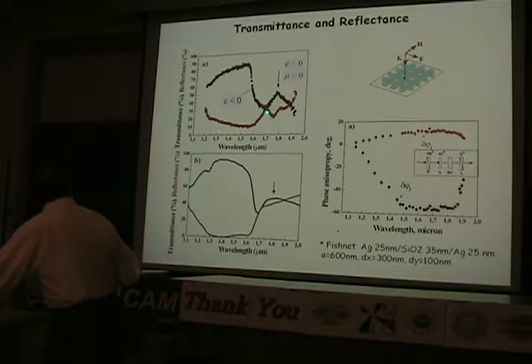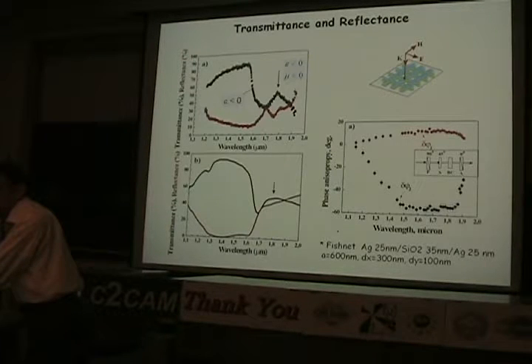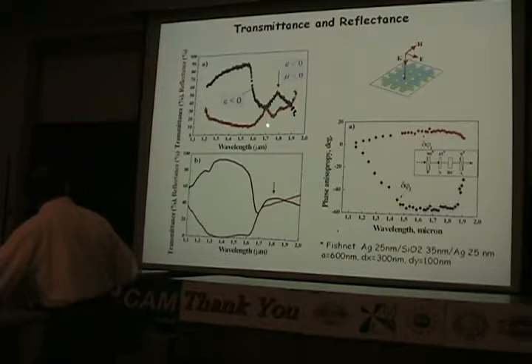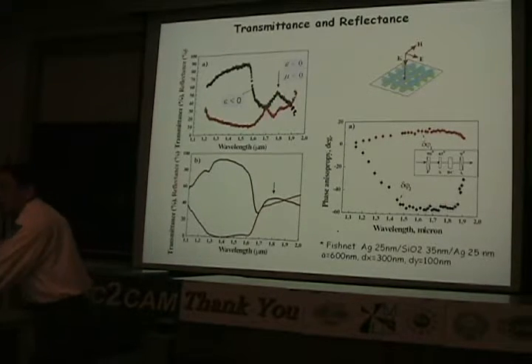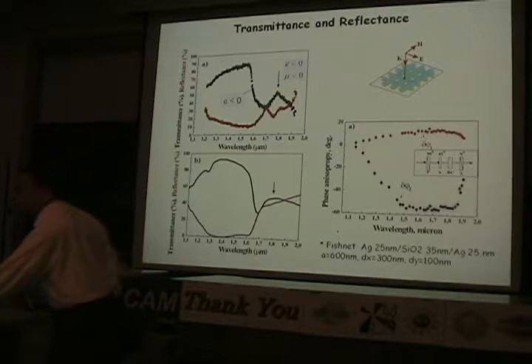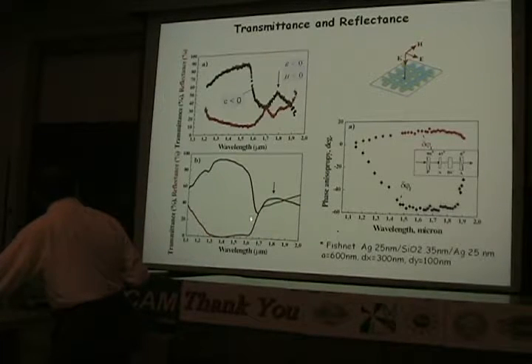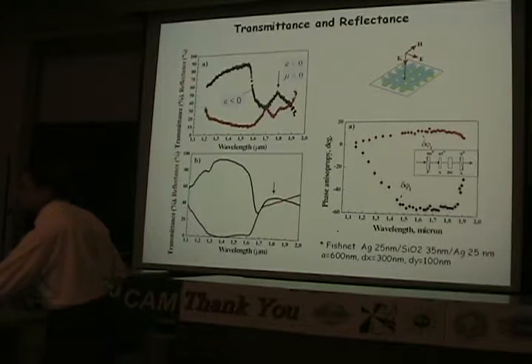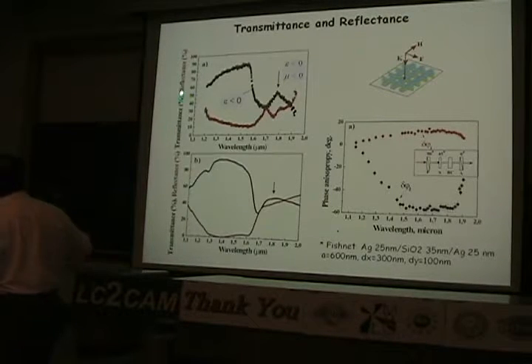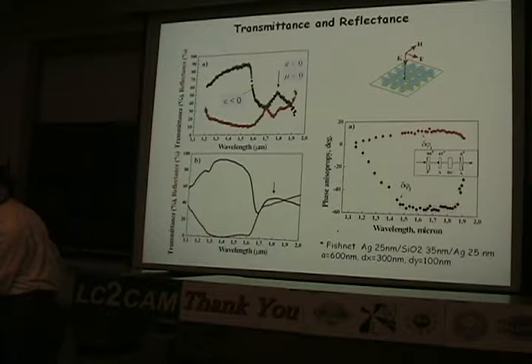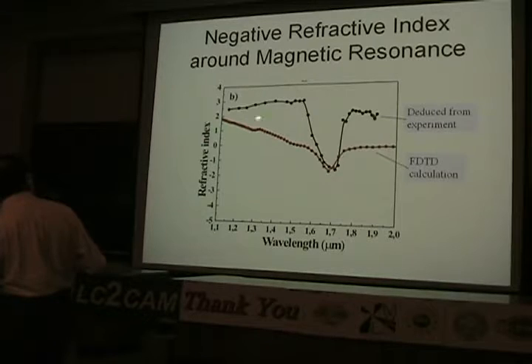But then, starting here, you have mu less than 0 because of the magnetic resonance. And now we have epsilon less than 0 and mu less than 0, and the wave becomes propagating slowly. So that's why the transmission starts to rise again. So this is the theoretical calculation. It matches pretty well. And the phase measurements, again, for the reflection and transmission curve. So from those measurements, the transmission and reflection coefficients, we should be able to deduce the refractive index. And here is the refractive index, and you can see that 0 is here. So in this particular range, the refractive index is negative.